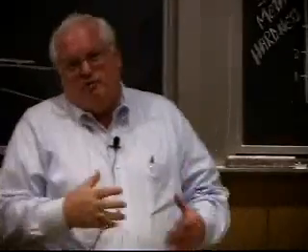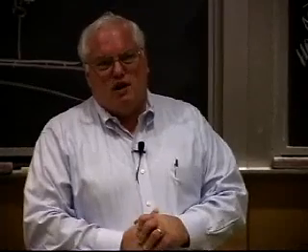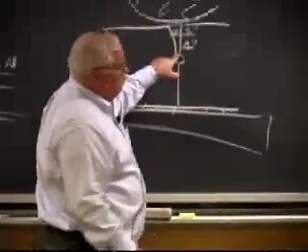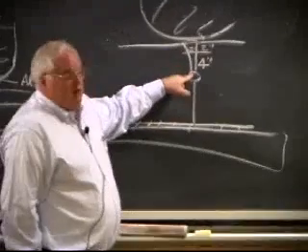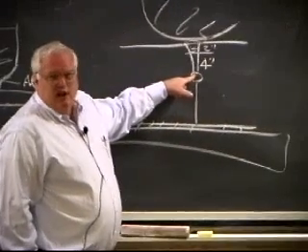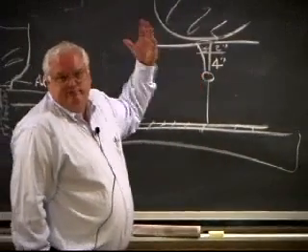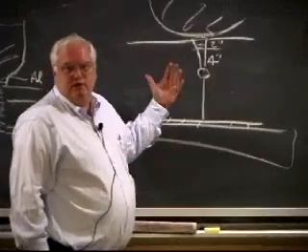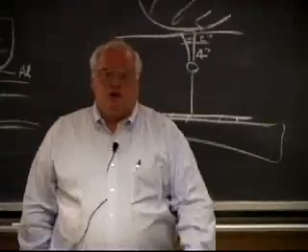Okay, so now we've just reduced our stress concentration. And it turns out if you get 6 inches deep down here where the drilled hole is, the stresses are down to like 25 KSI. 25 KSI in 140 KSI material, you'll never get fatigue. You're below the fatigue limit.